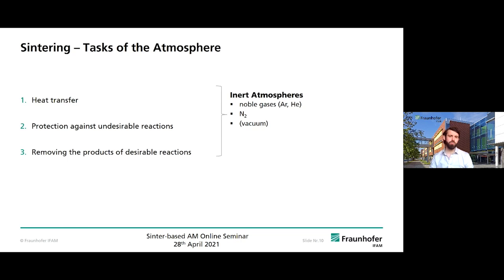This can be done mostly with inert atmospheres: noble gases like argon, or more or less inert nitrogen can be used, as well as vacuum. But vacuum cannot transfer heat over the whole temperature range. There is no convective heat transfer in vacuum, so heat radiation is the only possibility, and this does not really work for low temperatures. As well, removing products from the parts is also not really possible with vacuum to a certain extent.